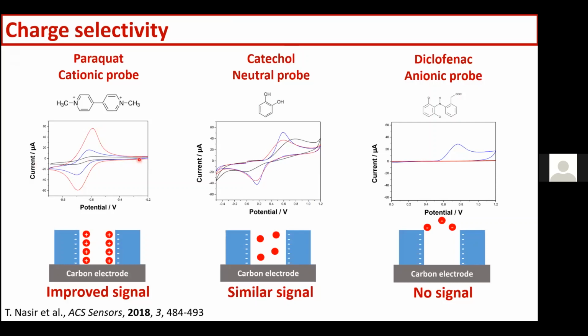before surfactant removal. And you can see with paraquat that we get a larger signal with the film than with the bare electrode, suggesting that we have some electrostatic interaction between the negatively charged silica layer and the cationic probe. If we look at catechol, it is neutral and is not much bothered by the presence of the film. We can see that the peaks are slightly broader and a bit lower, but we still see a good signal. Whereas in the case of diclofenac, the electrochemistry is completely suppressed by the presence of the film. So this suggests indeed that we have electrostatic interaction and electrostatic accumulation of the probe in the films.